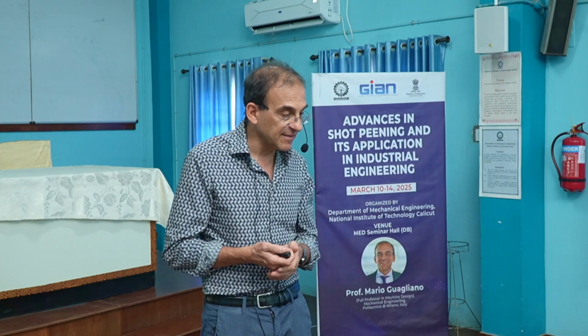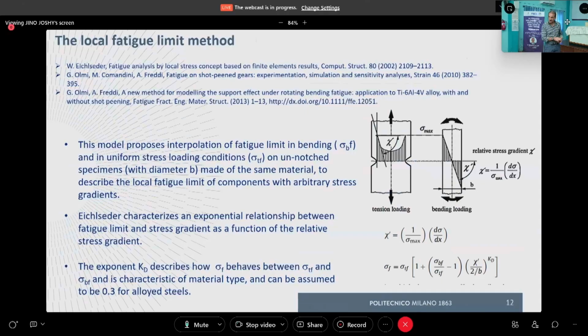And they say that indeed the fatigue limit of the part is equal to what? To the fatigue limit of the material, sigma Tf, that multiplies this formula, where sigma Tf is the fatigue limit in tension, so the axial fatigue strength. And the axial fatigue limit multiplies what? 1 plus the ratio between bending and tensile fatigue limit, minus 1, that multiplies the relative stress gradient times the radius of the part, at an exponent kd that is a function of the material, that for steel is generally considered approximately equal to 0.3.